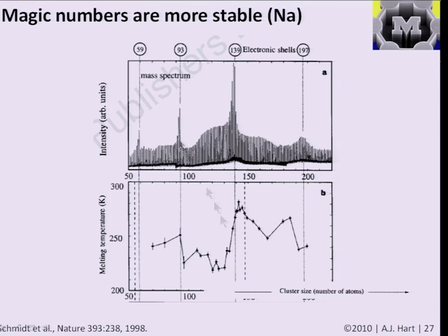And then they did studies of the melting point of these different clusters, and in fact found that the structures that are closed, that are more stable, have a higher melting temperature than the ones that are less stable. And just from a purely qualitative point of view, we can now kind of imagine why that's true, because the energy change needed to melt a cluster which is less stable due to its configuration of atoms would be lesser than one that is more stable.